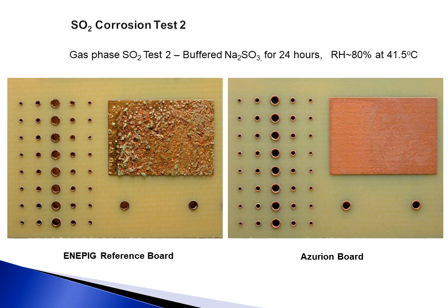We then carried out another sulfur dioxide corrosion test, where we changed the environment to a sodium sulfite solution. Left that for 24 hours, high humidity, and at a raised temperature of 41.5 degrees. Again, after the test was completed, you can see that the coated board has no signs of any blemishes on it, whereas the ENEPIG board is totally destroyed as far as soldering is concerned.